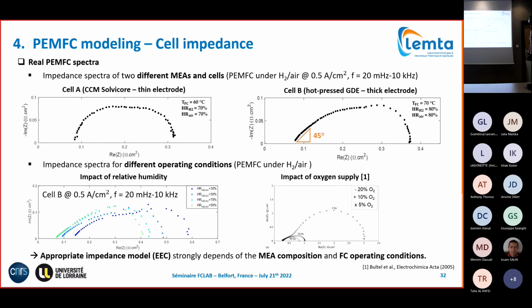Another point is that the overall shape of the spectrum will correspond to the different materials you use as well as to the operating conditions. For example, here on the left side you see a spectrum that we measured with a commercially available MEA, which has very thin electrodes. When you have very thin electrodes, you have a very small contribution to ion conduction. So the electrode thickness plays a role at the highest frequencies. So we will have more or less a 90-degree vertical intercept with the real axis at the highest frequencies.